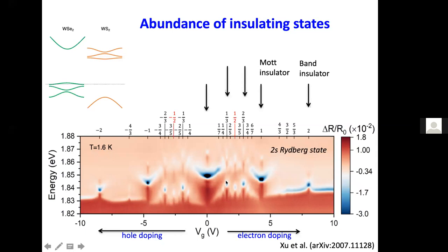First of all, when V is much larger than T, we get the Wigner crystal states. When V is not much larger than T, then you can get the charge density wave, because the modulation of charge density is reduced from the Wigner crystal. And then the question is, what's happening in between, for example, those insulating states, and that's kind of a mixture of the different charge order states. Let me put it that way.